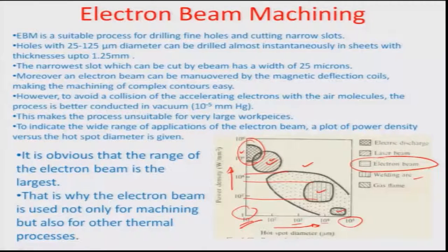So e-beam is obviously a much more suitable process for drilling fine holes and cutting narrow slots. Whatever can be done with a welding arc or a gas flame can almost always be done with e-beam machining. So holes with a diameter of about 25 to 125 microns can be drilled almost instantaneously in sheets of thickness up to 1.25 millimeters. This is the power of e-beam.